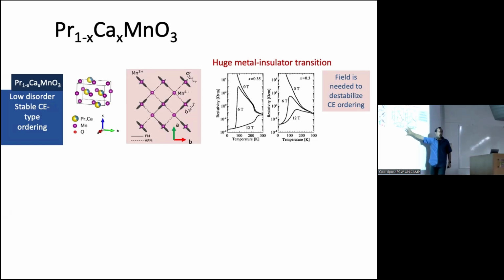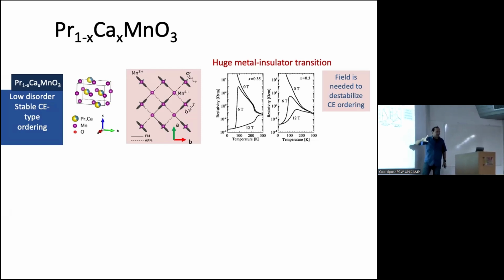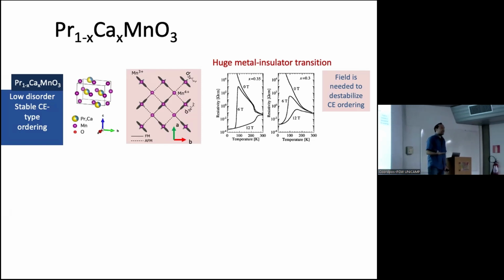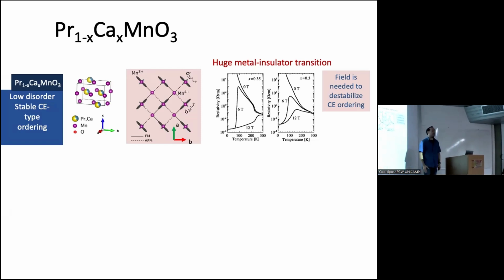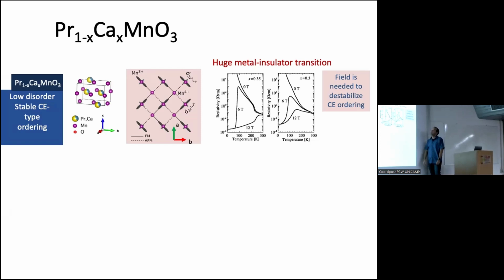So this material behaves as the vanadium oxides that I talked about, except that you have to apply a magnetic field. So you apply a magnetic field, you sweep the temperature, it does exactly the same. It has a huge transition in the conductivity.